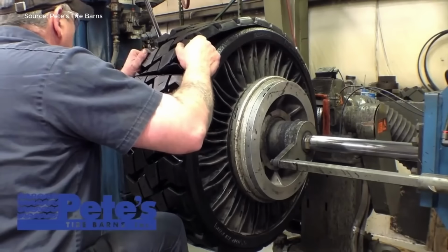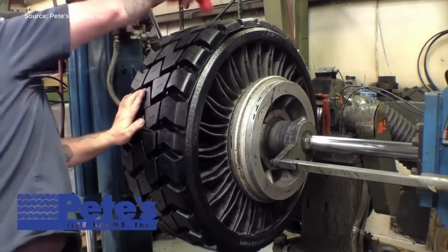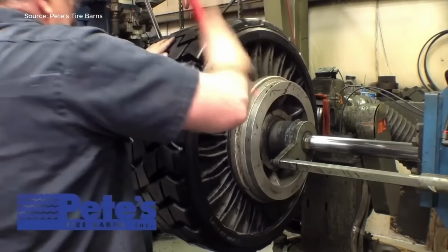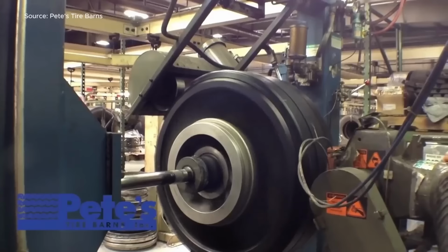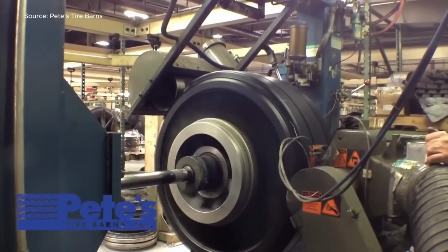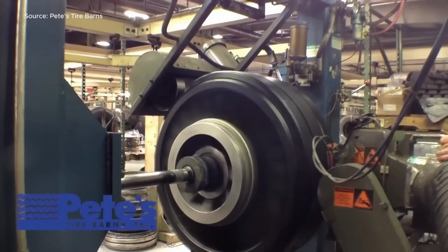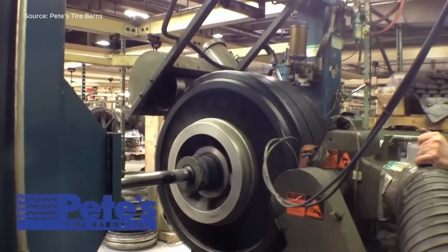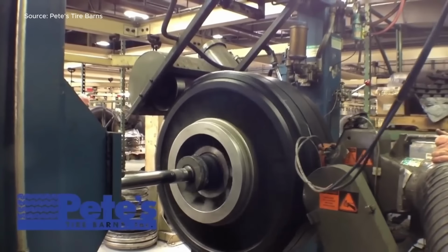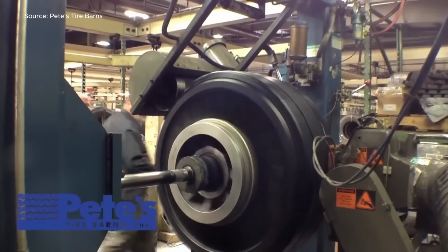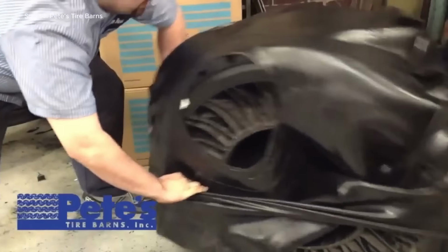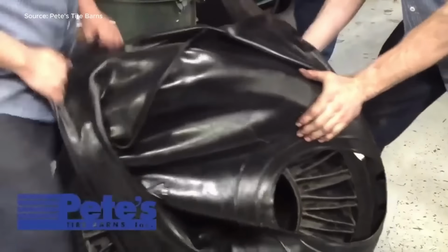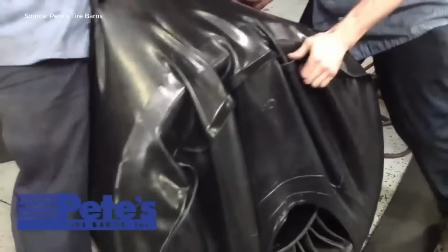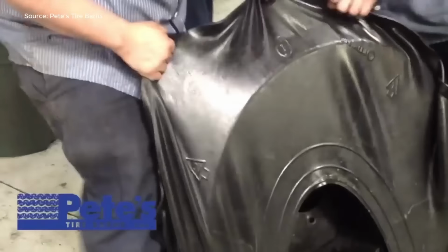Before curing, air is removed. The sleeve is vacuum sealed to pull the rubber tightly against the tread, eliminating voids or bubbles. The entire assembly is then placed into a curing chamber. Over 4 hours of heat and pressure fuse the new tread to the structure. A timer is set, but temperature and pressure are constantly monitored and logged. If the pressure drops mid-cycle, the batch is flagged for inspection.